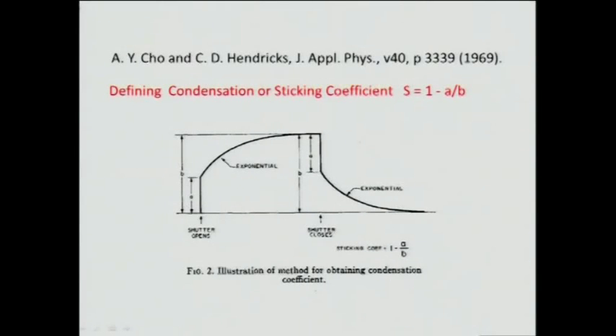In surface physics, at that time, we called it the sticking coefficient, equal to S = 1 - A/B, where A is the abrupt change in the magnitude of measurement when we open the shutter of the molecular beams, and then it goes through an exponential equilibrium section. And then when we close the mechanical shutter, the structure reverses.